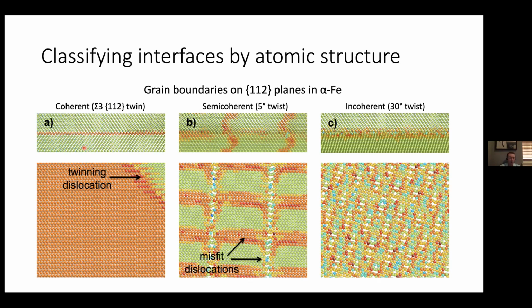And if you look closely, you'll see that you have rows of atoms coming in sort of diagonally here on the bottom, and then they're coming out diagonally on the top, but in the opposite direction. That's sort of a characteristic of twins. And twins, you can think of them as sort of mirror reflections of grains about a particular plane. So in this case, you've got a mirror reflection of the structure of one grain about a 112 plane. That's a twin boundary, right?